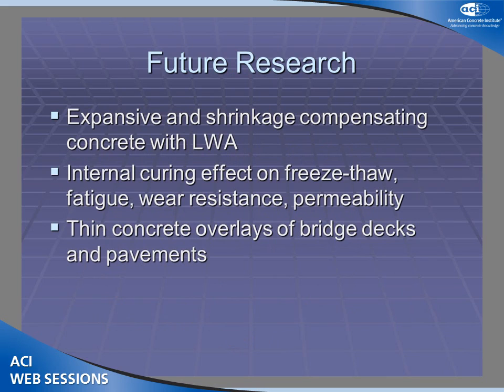So I think there is a lot of potential to look at some of these expansive and shrinkage compensating concretes combined with the lightweight aggregates and see if you can deal with some issues. We haven't really looked at the effect on freeze-thaw. I understand other people have, in terms of fatigue, wear resistance, and permeability. And I really think a place that we could make a lot of use out of internal curing is thin overlays on both bridge decks and on pavements that are known to be problematic from the standpoint of delaminations.